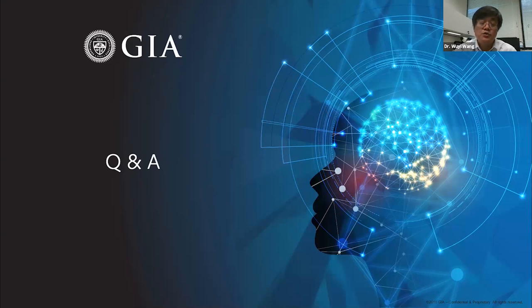For synthetic diamond, actually the same principle applies. Let's say it's a very subtle yellow synthetic diamond, either HPHT synthetic or CVD synthetic with some isolated nitrogen. Immediately after irradiation, it could be still green or bluish green, greenish blue color. That's a stable color if we don't heat it. But if this diamond is heated as we did to the natural diamond, these stones will all turn to a pink color. So it depends on how you define the heat and the heat temperature and also the starting material. The color will change for both natural and synthetic.